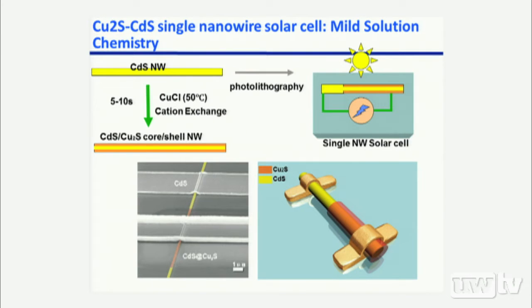In this example, we start with the cadmium sulfide nanowire, and utilize this very low temperature cation exchange chemistry developed in Professor Peidong Yang's lab back in Berkeley. All you need is to dip these nanowires in a copper chloride solution at 50 degrees for a couple of seconds. You turn this wire into a junction. The surface now becomes copper sulfide. It's a copper sulfide, cadmium sulfide junction.